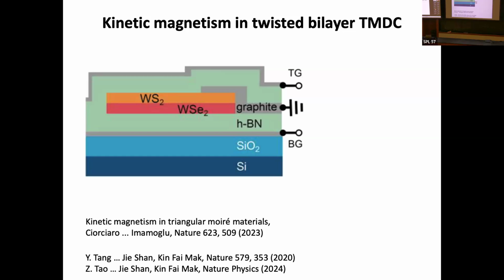You can take these 2D materials, an example here being the transition metal dichalcogenides. You can stack them on top of each other and twist them relative to each other, and you get effective moire lattices. And in these materials, you can get, for example, a triangular lattice where the interactions are very strong due to the presence of a flat band.